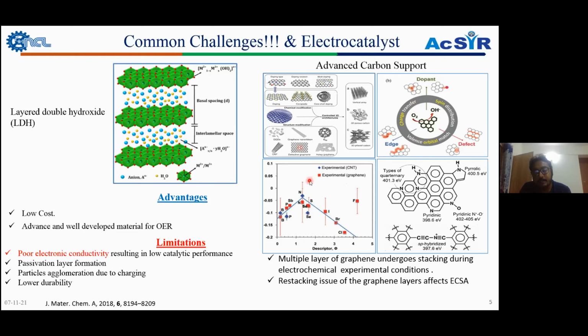The second thing is that various heteroatoms can be doped, like boron, phosphorus, tin, iodine, bromine, but theoretically and experimentally, nitrogen doping shows better electrochemical, better electronic property modulation. So nitrogen doping could be a better option over the carbon substrate. Further, nitrogen can be doped in graphene in various forms: during nitrogen doping it can form pyrrolic, pyridinic, or quaternary nitrogen. Based on that, the activity as well as the durability can be altered.